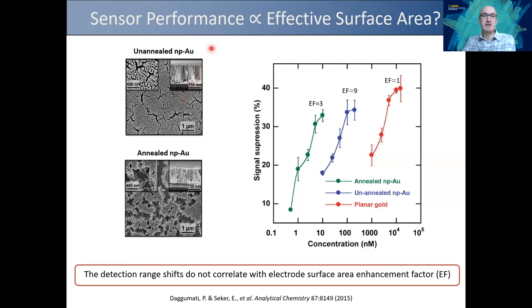So one thing that is really a notion in the electrochemical detection field is that effective surface area is the reason why the nanostructured materials improve the limit of detection. However, our studies show that this is basically the concentration of the target molecule that you introduce, and this is the signal suppression, basically detection. Higher signal suppression means basically you are detecting, and you can see as we reduce the concentration of the target, the signal decays.